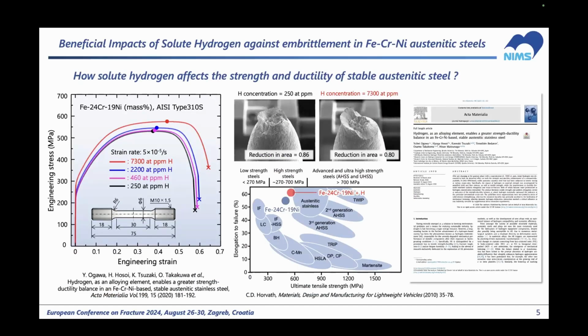So now I will show you a typical example of the iron, 24% chromium, 19% nickel steel. And I have to emphasize that this is not any special or originally made material, but just one of the commercial type austenitic stainless steels, 300 series austenitic stainless steels. What happened by hydrogen?